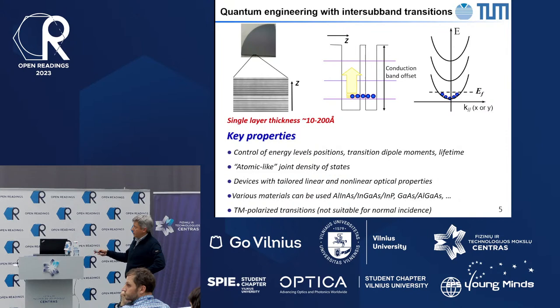And by playing with the thicknesses of these quantum wells and quantum barriers, you can build the wave functions for the electrons in this semiconductor heterostructure. And you can artificially design this energy level configuration for a wide range of applications. Quantum cascade lasers that we mentioned are built using this technique, but you could do much more than quantum cascade lasers. You can control energy levels, positions, transition dipole moments, and electron lifetime by playing with the thicknesses of wells and barriers. And these materials can be pretty heavily doped.